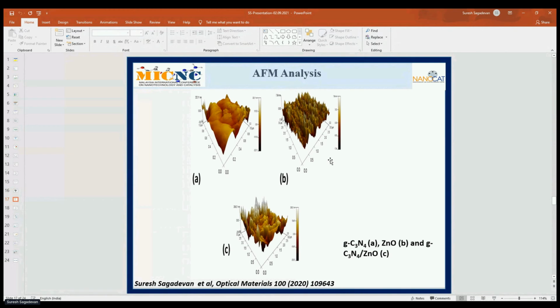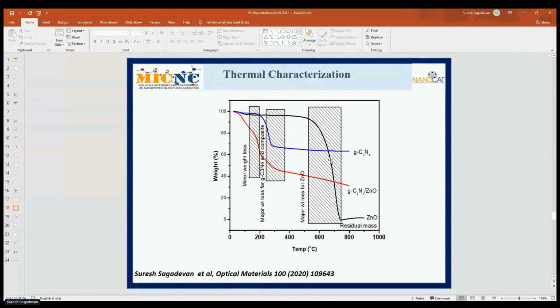and the composite. Next, we performed the thermal characterization, the comparison of TGA analysis for zinc oxide, graphitic carbon nitride, and then the graphitic carbon nitride with zinc oxide composite. You can see the figure. This analysis is divided into three parts. The first one is a minor weight loss, the second one is a significant weight loss, and the third one is a reduced mass. You can see that at 180 degrees Celsius, a minimum weight loss is occurring